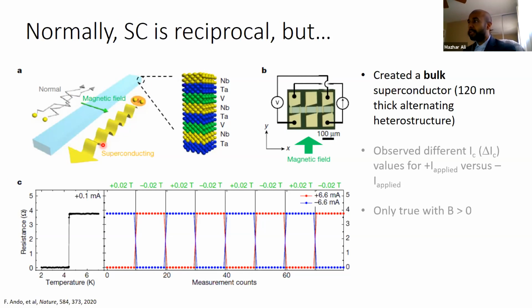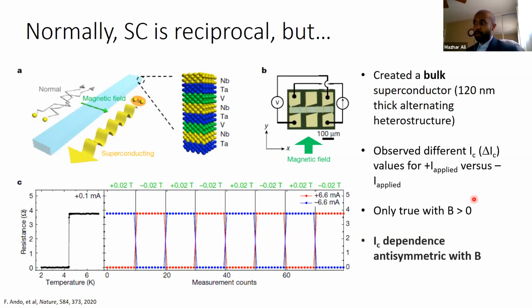Now, this was a repeating thin film of niobium, tantalum, and vanadium that was like 120 nanometers thick. And they essentially saw a delta I, as in the critical current to the right was not the same as the critical current to the left. But they only saw that with a magnetic field. And that's very important, because this entire mechanism was based on something called Magnetochiral Anisotropy, which we'll talk about in a second. But the important thing is that the critical current dependence was anti-symmetric with the magnetic field.